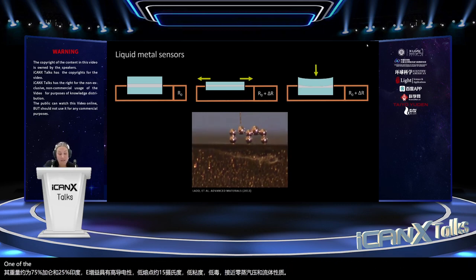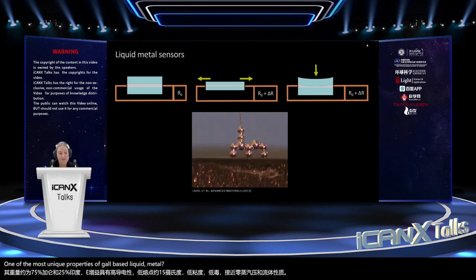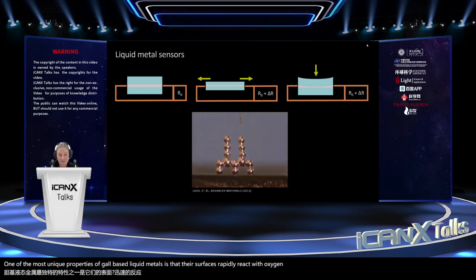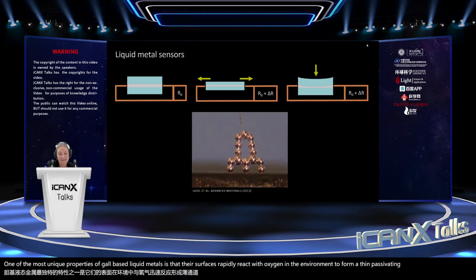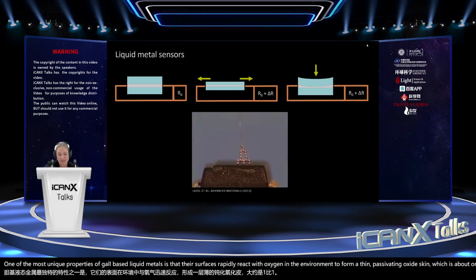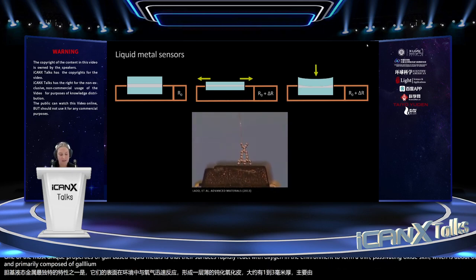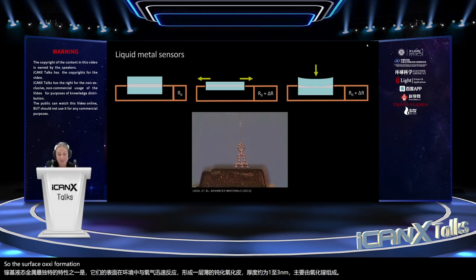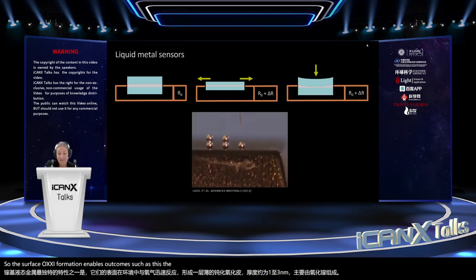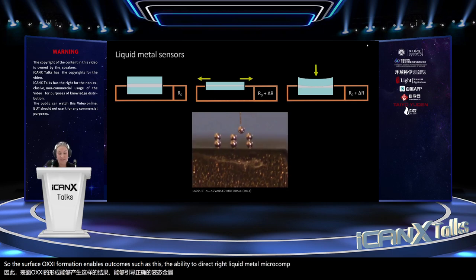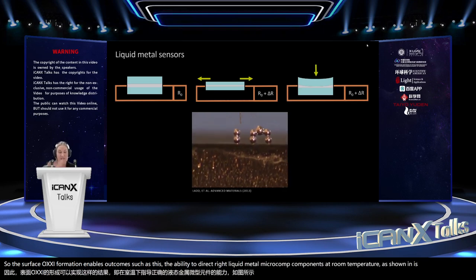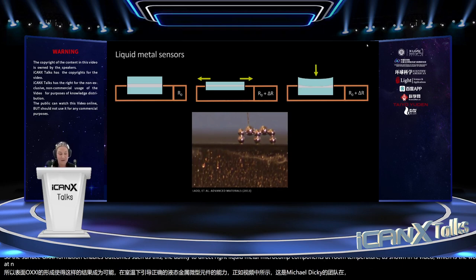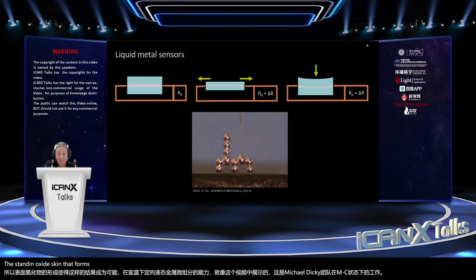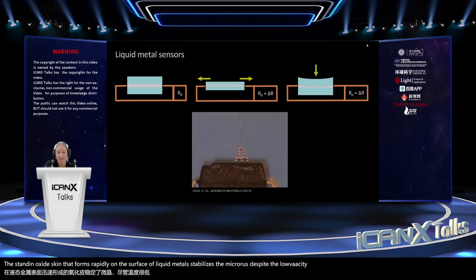One of the most unique properties of gallium-based liquid metals is that their surfaces rapidly react with oxygen in the environment to form a thin passivating oxide skin, which is about 1 to 3 nanometers thick and primarily composed of gallium oxide. So the surface oxide formation enables outcomes such as this, the ability to direct write liquid metal microcomponents at room temperature, as shown in this video, which is the work of Michael Dickey's group at NC State. This thin oxide skin that forms rapidly on the surface of liquid metal stabilizes the microstructures despite the low viscosity and large surface energy of the liquid.